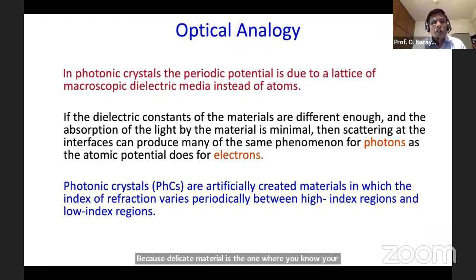Okay, right? So your light passes through, but it can also get reflected because of the index contrast between the sphere and the surrounding medium. So the light can get scattered, refracted, and so on. There are many ways for the light to go through. So you use a dielectric medium, or dielectric spheres, which are separated from each other by certain spacings of a few hundred nanometers. Then you will experience a photonic crystal.